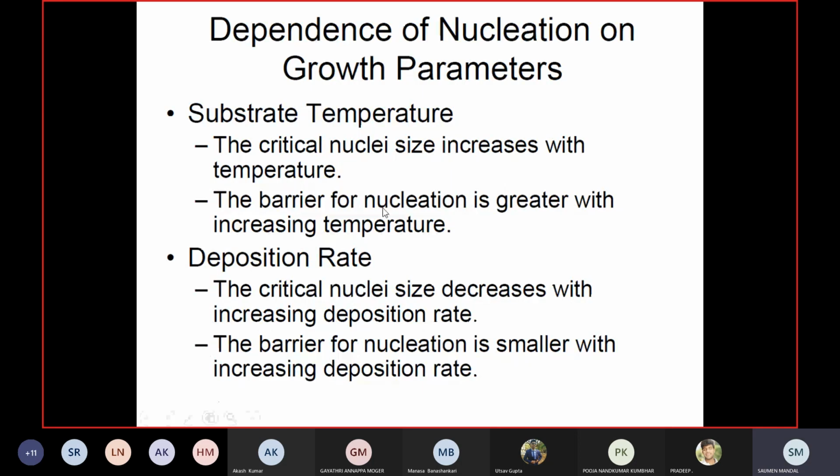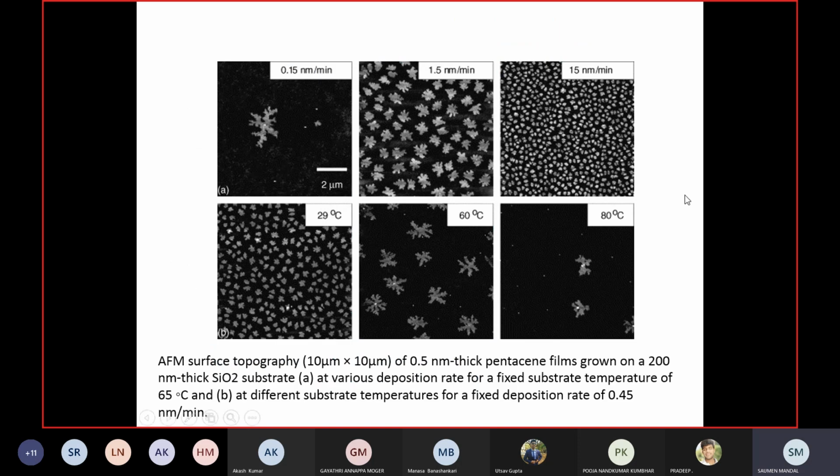So that's why, if you do physical vapor deposition, these two parameters are extremely important. Now, if I want a single crystal, can anyone tell what my approach will be? Just seeing the picture, I want a single crystal. What will be my approach in physical vapor deposition? How to get a single crystal? In which condition? Just think about it. From the figure, higher temperature and lower deposition rate. Correct. Exactly. If we maintain that, we can go for a single crystal.